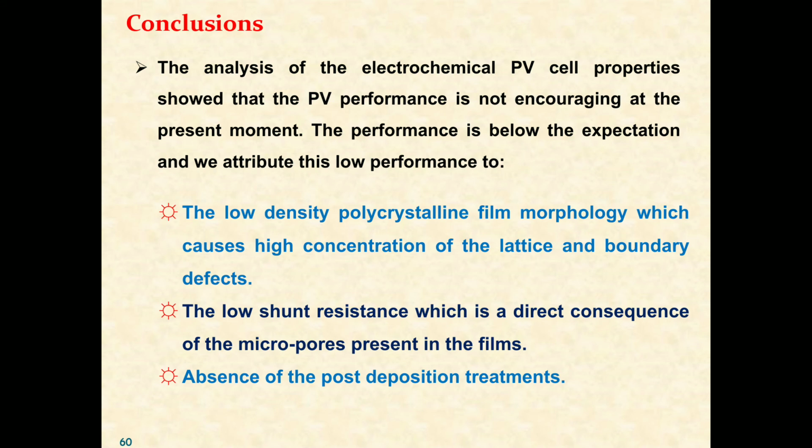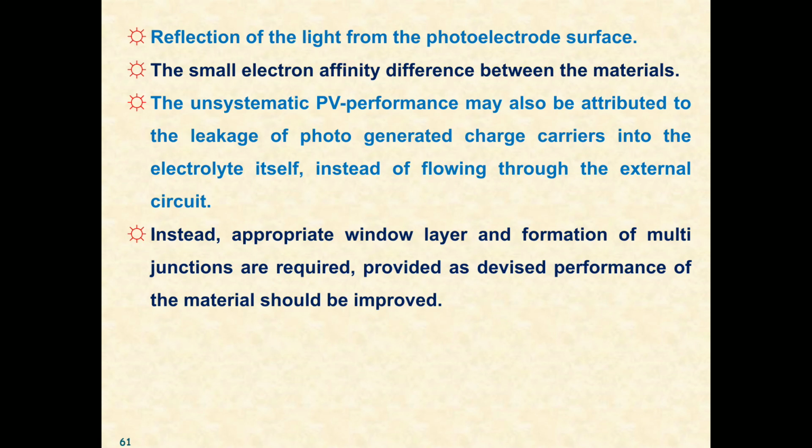The low shunt resistance, which is a direct consequence of the micropores present in the films, the absence of post deposition treatments, and the reflection of light from the photoelectrode surface.